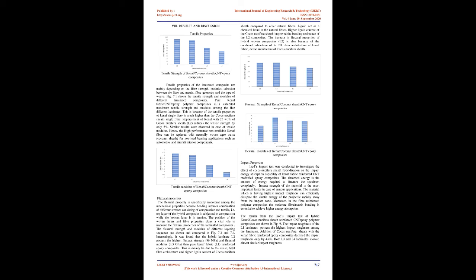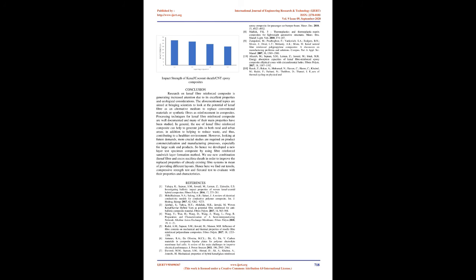Results and discussion. Tensile properties. Tensile strength of Kenaf/coconut sheath/CNT epoxy composites. Tensile properties of the laminated composite are mainly depending on the fiber strength, modulus, adhesion between the fiber and matrix, fiber geometry, and the type of weave. Fig 7.1 shows the tensile strength and modulus of different laminated composites. Pure Kenaf fabric/CNT/epoxy polymer composites, L1, exhibited maximum tensile strength and modulus among the 5 different laminates.